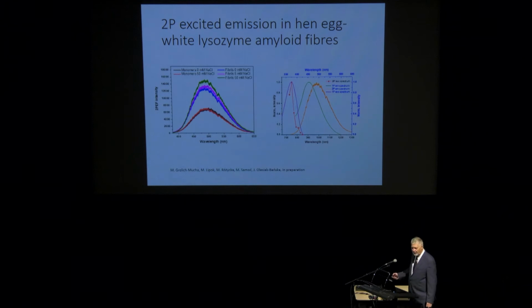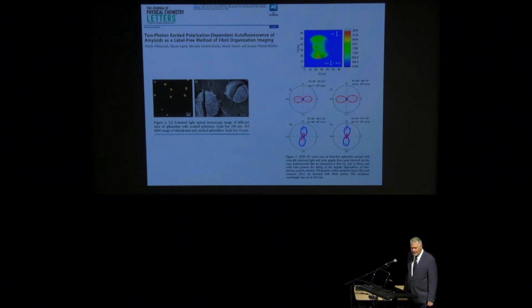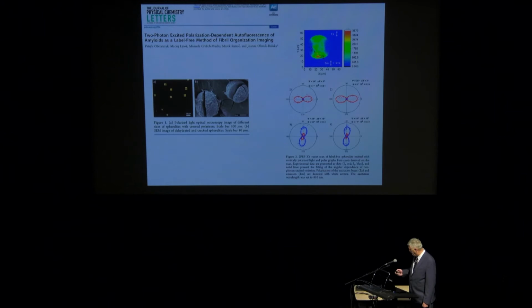This is a paper that we haven't published yet, but in this paper we show that amyloids show 2-photon induced luminescence, that is at around 500 nanometers. And we can excite it at around 750 nanometers. It's a relatively strong two-photon absorption. So this sort of effect can be used for imaging amyloids. That can be even used for assessing orientation of things which are on sub-nanoscale, using polarization analysis of the two-photon excited luminescence that comes from these amyloid structures.